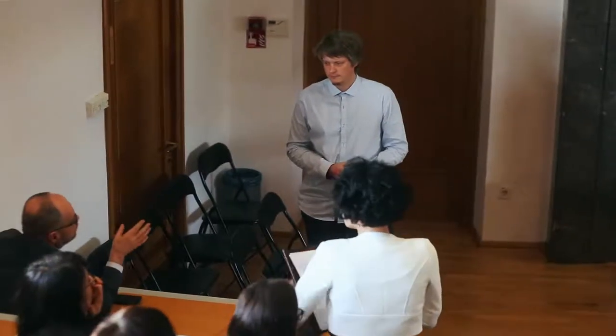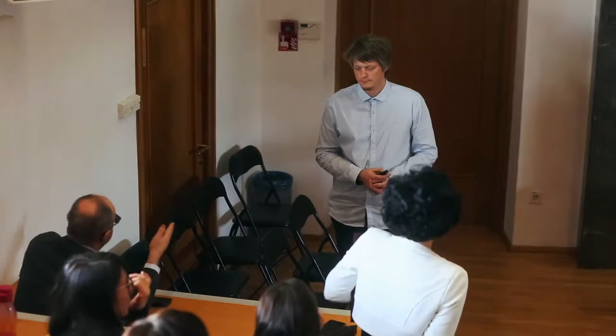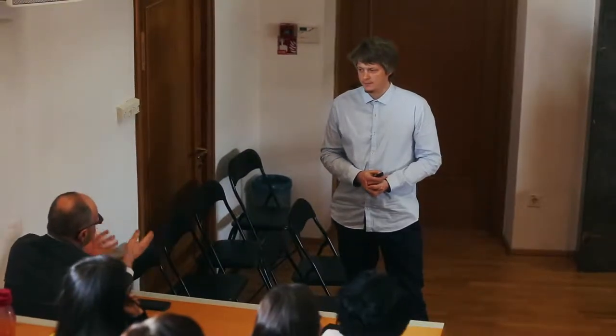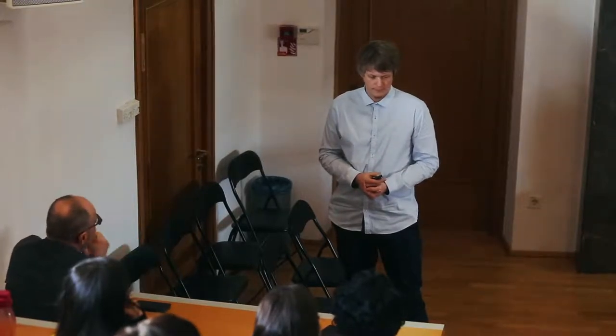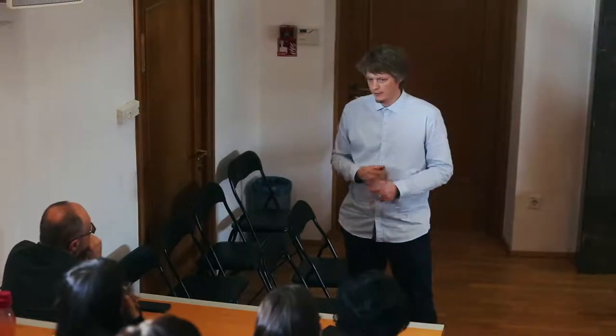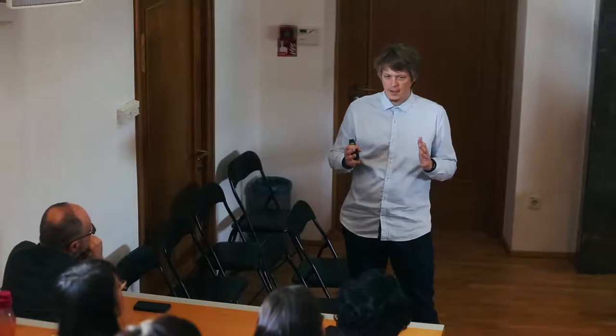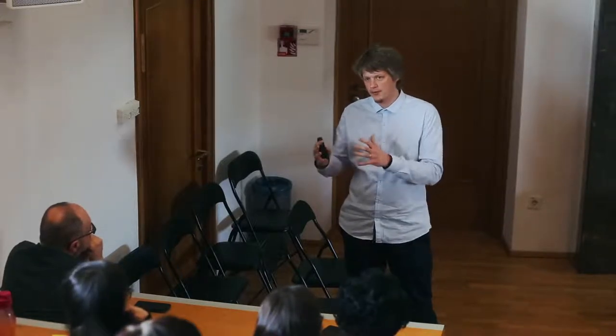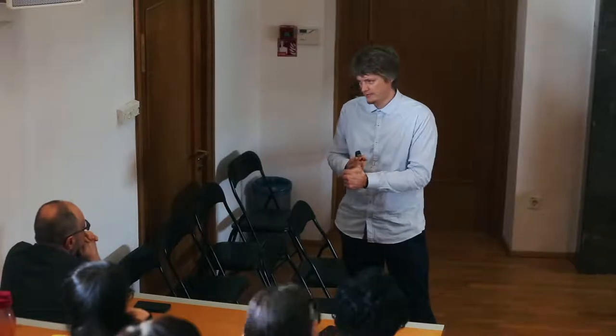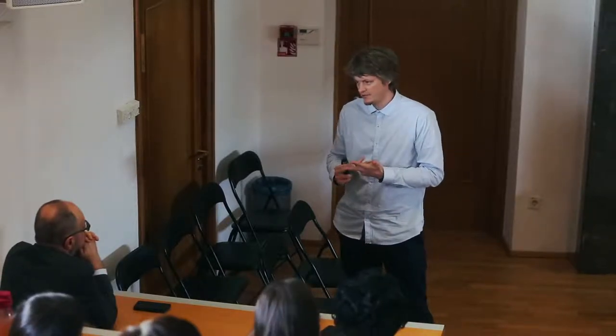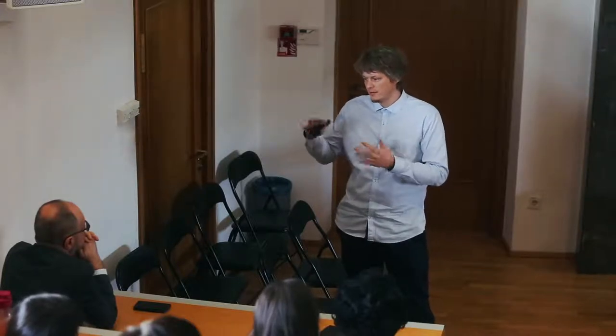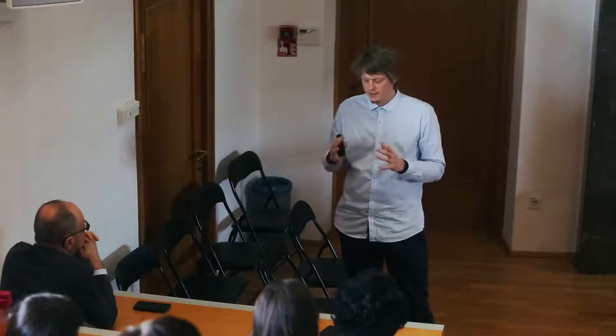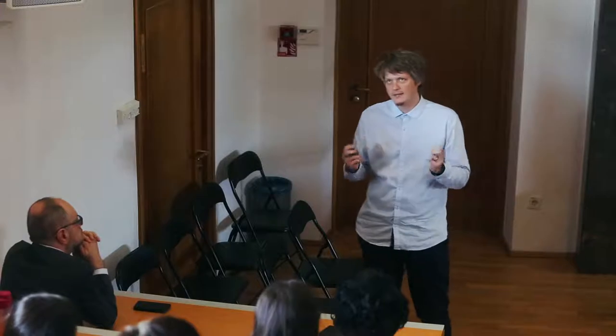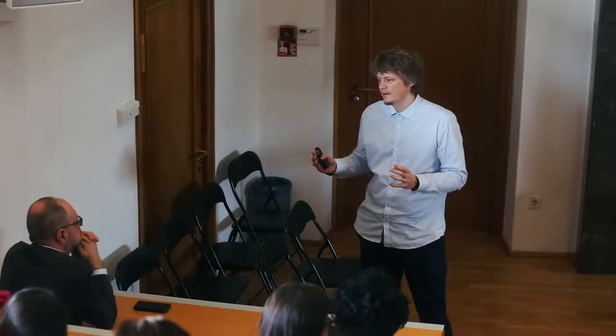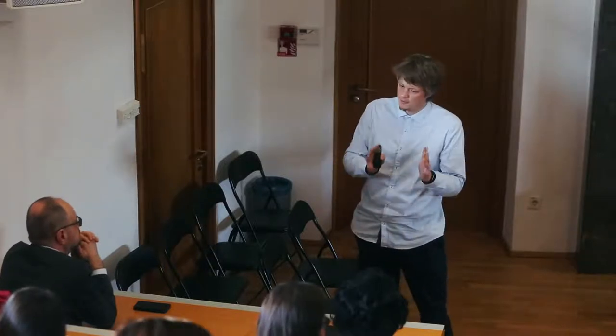Thanks for the nice lecture. I didn't quite get the physical meaning of parameter A, which is a key parameter in your equation. And especially, how reliably can you determine it? Because everything probably depends on that. Yeah, that's correct. It's very important to determine it correctly. But actually, in this parameter A, everything is packed. So mostly experimental parameters. For the NMR experiment, we need to spin the sample, so spinning frequency is important, and also recoupling efficiency. And then the other parameters, let's say the dynamics of the structure, because these linkers are not just static. So it has to be fitted on samples from the same family, so that you have basically the same dynamics, with the same experimental equipment and the same conditions.